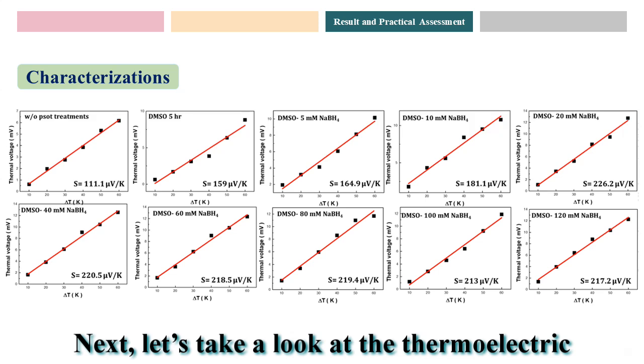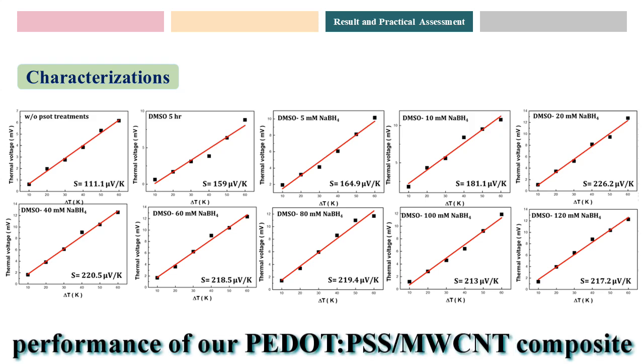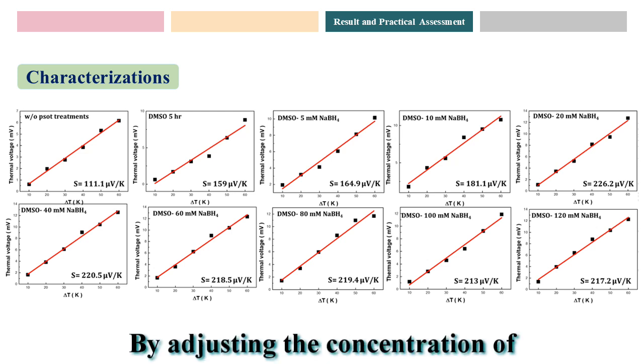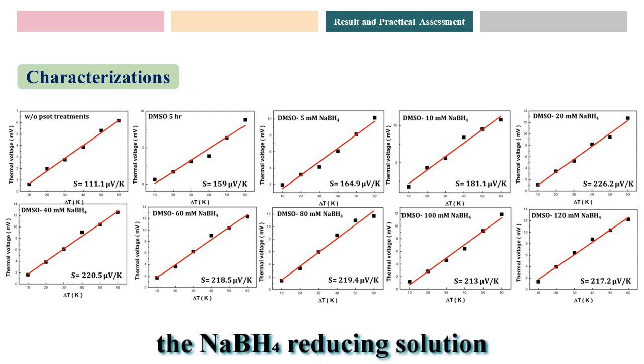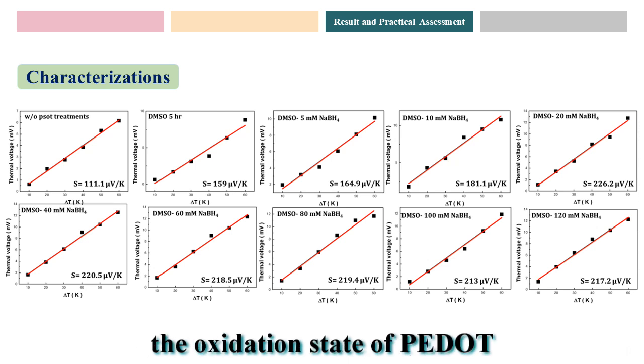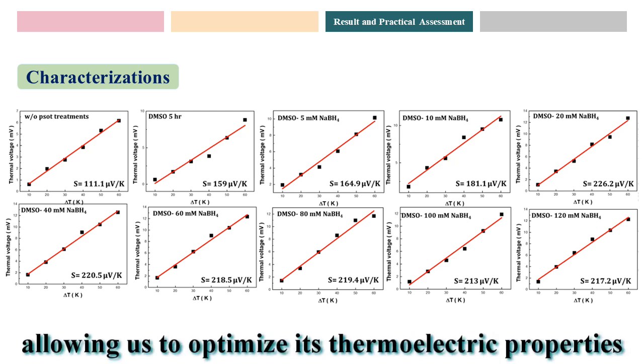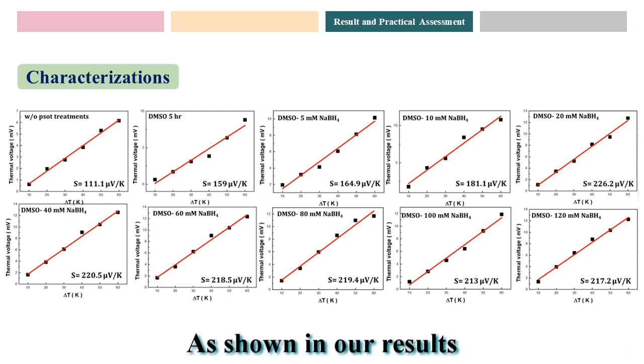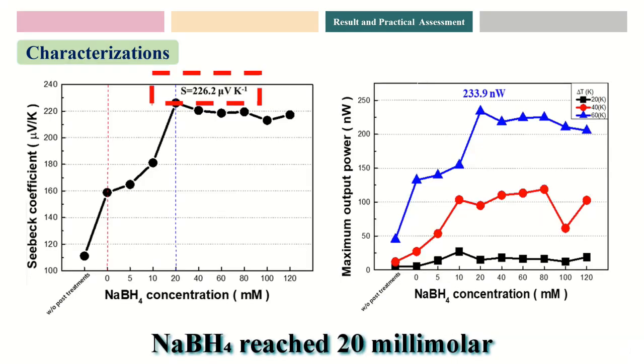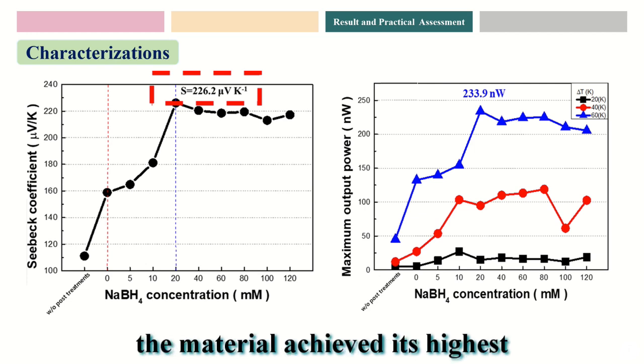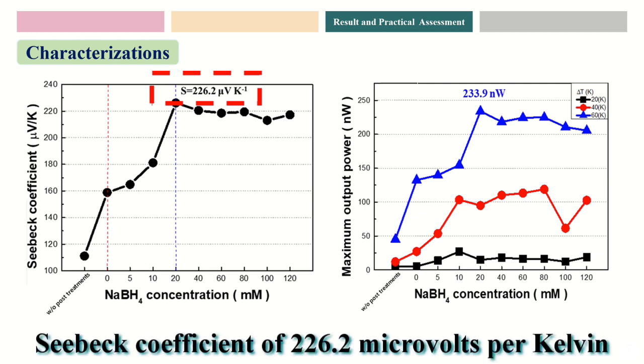Next, let's take a look at the thermoelectric performance of our PEDOT:PSS multi-walled carbon nanotube composite. By adjusting the concentration of the sodium borohydride reducing solution, we were able to precisely control the oxidation state of PEDOT, allowing us to optimize its thermoelectric properties. As shown in our results, when the soaking concentration of sodium borohydride reached 20 mmol, the material achieved its highest Seebeck coefficient of 226.2 microvolts per Kelvin.